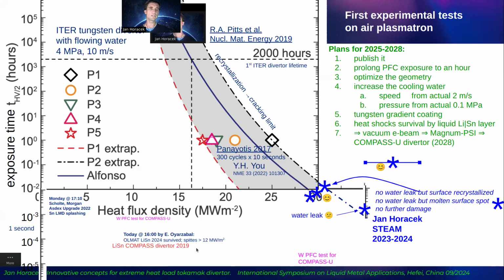What's achieved using the liquid metals was values much lower than this, much shorter times, like a fraction of a second. That's also what we did on COMPASS, really short times, unfortunately. And already above 10, 12 megawatt per square meter, we get problems. And what we achieved in Germany in 2022 was even much lower heat fluxes and shorter times. But what we did now with our steam experiment, we got much above these values.